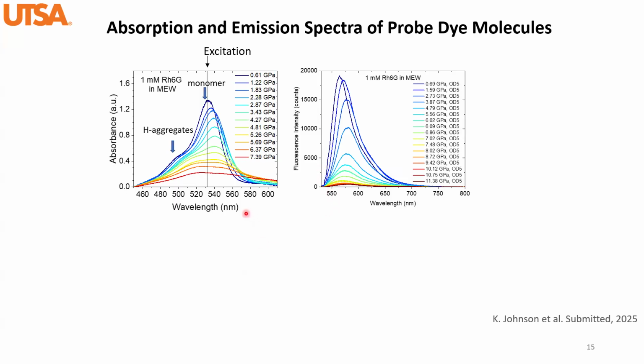I know that there is quite some research focusing on the rhodamine 6G molecules under high pressures, but probably not at this concentration, not at this high pressure. So in our case, we take a look at the dye molecules in methanol, ethanol, and water, and we have the absorption spectrum shown on the left and the fluorescence spectrum shown on the right. Again, the laser was at 532 nanometers to excite the emission.